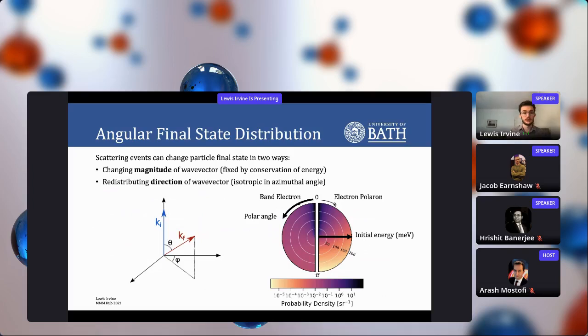So we decided to look at the angular distribution of the final states after scattering. Once you have a scattering event, the particle has an initial wave vector, and a scattering process can do one or two things. It can change the magnitude, so you can gain or lose energy, and it can also redistribute the direction of that wave vector, so it can scatter it by an angle. You can imagine when we work out the mobility, if you get large angle scattering, that can reduce the mobility significantly.